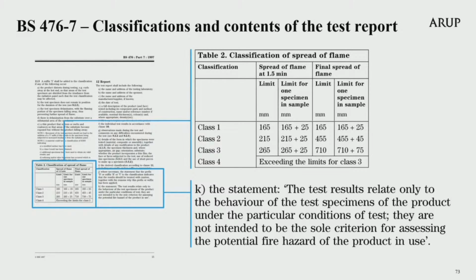Part 7 sets out 4 classifications based on the spread of flame at 1.5 minutes and the final flame spread after 10 minutes. These are Class 1, Class 2, Class 3 and Class 4, and the limits for each are on screen now. I also note that it is stated that this statement must be included in the test report. Again, the test results relate only to the behaviour of the test specimens of the product under the particular conditions of test. They are not intended to be the sole criterion for assessing the potential fire hazard of the product in use.